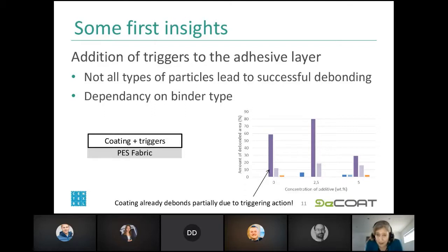I just gave one example where, in purple, we can already see, even if we don't add additives, that we already have a partial debonding of the coating. So that actually means that the coating itself does not resist our trigger. That also means that the quality of this coating could be lower. So you really have to fine tune.